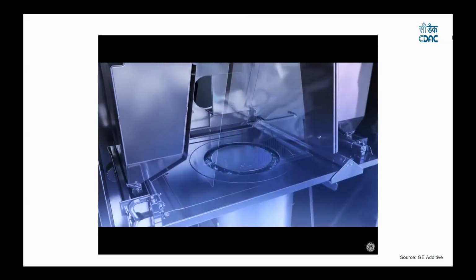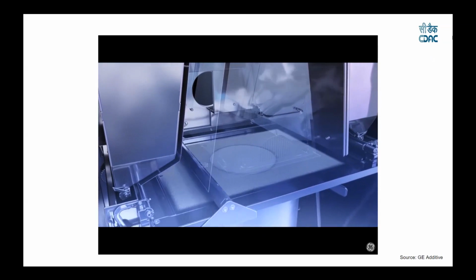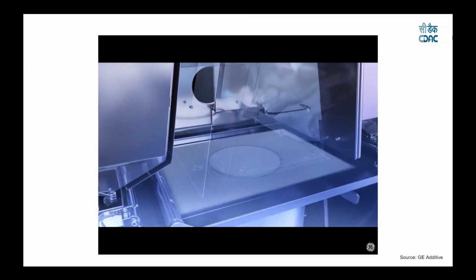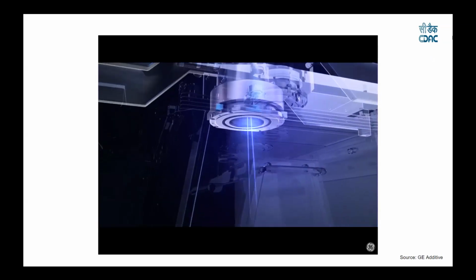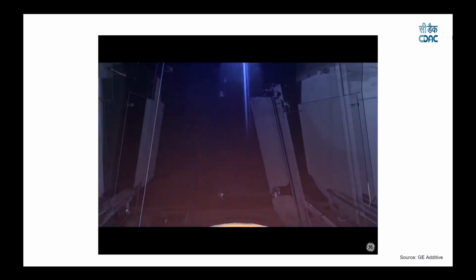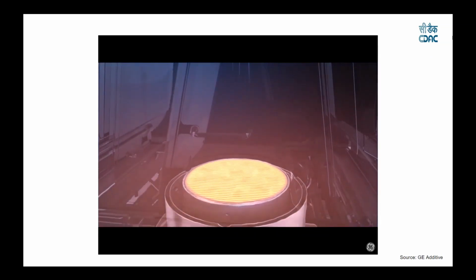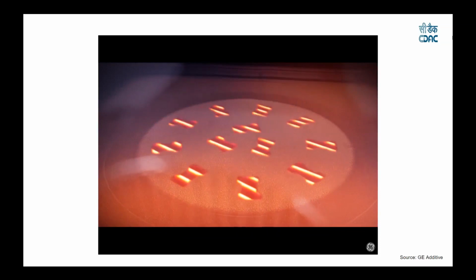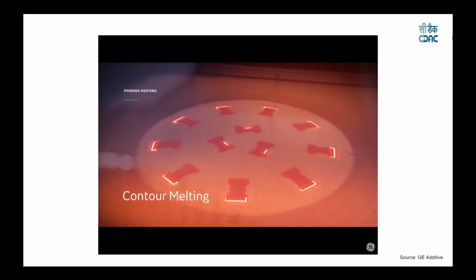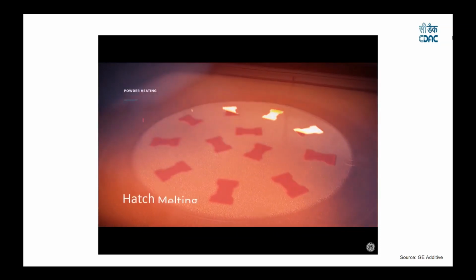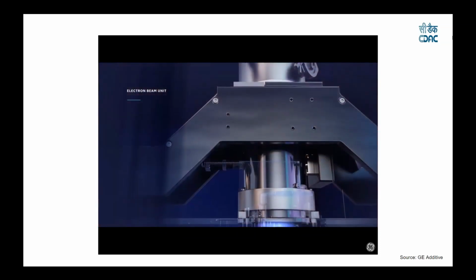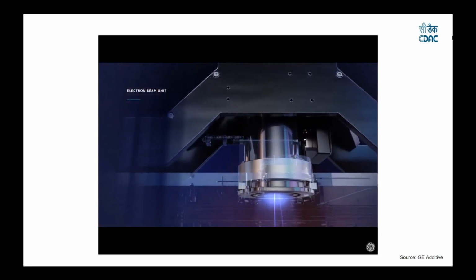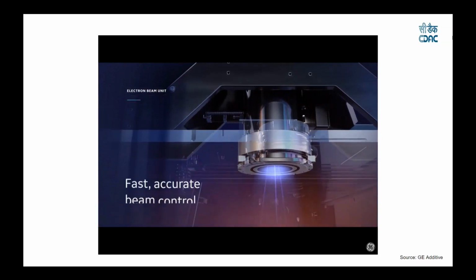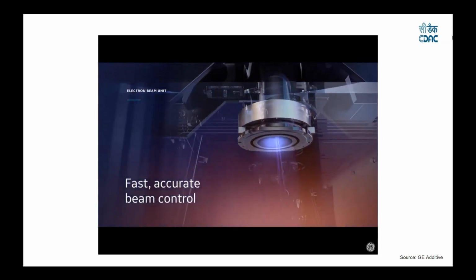Next, Arcam EBM's powder layering system evenly distributes a thin layer of powder on the build area. A powerful 6 kilowatt electron beam heats the powder bed to the optimal ambient temperature and then proceeds to melt the powder. First, contour melting, the electron beam countering the perimeter of the part, and then hatch melting, the internal area. The electron beam generating unit contains no moving parts, allowing for extremely fast and accurate beam control.